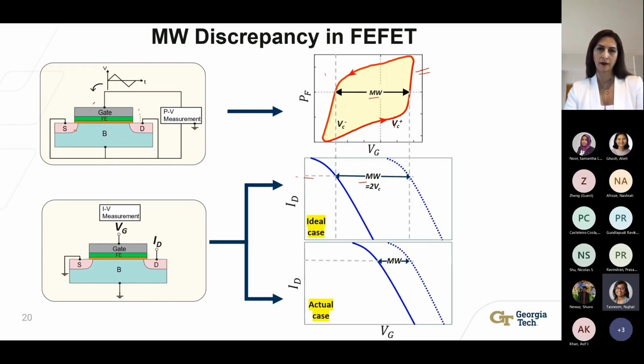So for example, if this is the positive coercive voltage and this the negative coercive voltage, and this is the program and erase voltage, then in the ideal case, the memory window we get from the IV curve should be equal to 2VC. However, as we've mentioned before, this is not something we see experimentally. So if we denote the theoretical memory window as delta VP and the experimental memory window as delta VT, what we end up seeing is that delta VT is much, much smaller than delta VP. And this is the memory window discrepancy in FeFET.